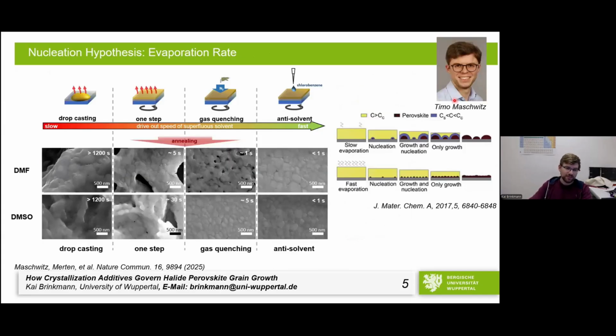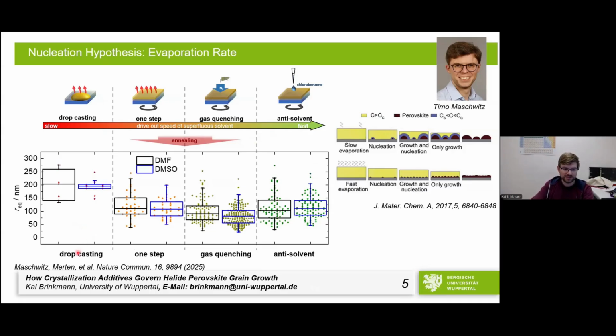And then Timo went to the lab, and one straightforward way to make sure that your speed of nucleation should change is to just change the deposition technique. And I wouldn't believe him when he came to me the first time telling me that all the grains are the same size. But we repeated this experiment, and even though they looked very different in terms of morphology, if he did the process parameters right, he was actually able to give me the same grain size, no matter if we would do drop casting, one-step deposition, gas quenching, or anti-solvent.